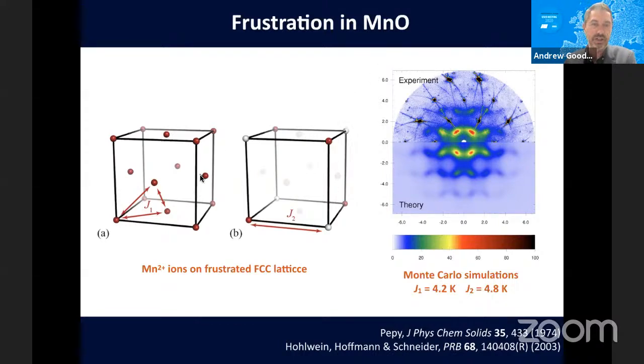So just to remind you of the underlying physics, MnO is a rock salt monoxide. The manganese sublattice is the FCC lattice that you see here. The dominant magnetic interactions are nearest neighbor antiferromagnetism and next nearest neighbor antiferromagnetism, J1 and J2. It's only the first of these that is frustrated, because you've got these triangles that you see here. The strength of these two interactions you can measure using, say, neutron inelastic scattering measurements. They turn out to be relatively similar in strength. You can use those two J values to calculate, say with a Monte Carlo simulation, the kind of magnetic structure you would expect within the paramagnetic regime.